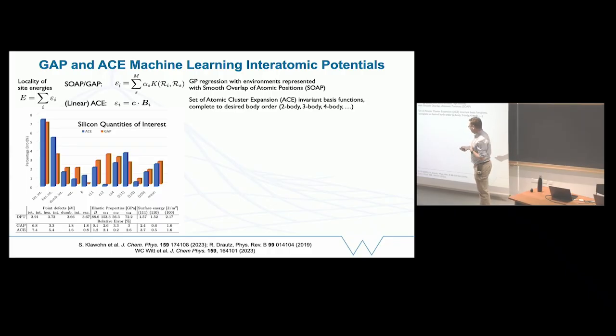So this is for silicon, a comparison of point defects, elastic properties, surface energies, a large range of quantities, and they're all within about 5% of DFT. This was based on a data set that we developed specifically for doing this with the GAP model. We just took that same data set and refit it with this new ACE model, and we get comparable accuracy.